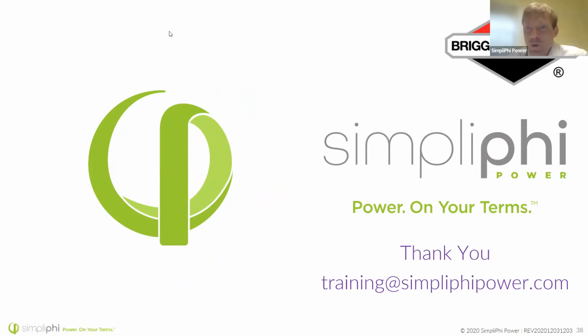Okay, just curious, would you equate LFP at 75% energy density compared to other formulations? How do LFP batteries stack up? Yeah, I think that's pretty close, Glenn. To give you an idea here, LFP batteries are a little bit heavier. You have an iron cathode there and you don't have the cobalt. The difference is that having the cobalt in the cathode makes a slightly higher voltage, and that higher voltage ends up meaning that you have a little bit more energy density. Now, that's not really important for home battery backup. But sometimes if you're trying to make a really fast, lightweight object, for example, a drone, you don't want that extra weight. And so I would say it's closer to 75 to 80% energy density.